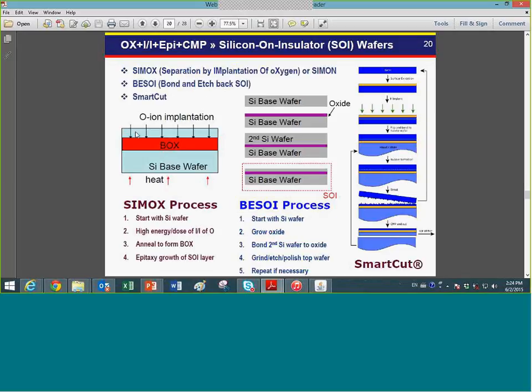And here are some examples of combining typical processes to enable some technologies. For example, to produce SOI wafers, you can use oxidation, ion implantation, epitaxy, and CMP. Here you use SIMOX, the implantation of oxygen into silicon, forming a buried oxide layer to form the SOI. If this layer is too thin, you can grow it by epitaxy. This one is the Smart Cut process: instead of implanting oxygen, you implant hydrogen and form a hydrogen bubble layer, then bond and separate to get the SOI.